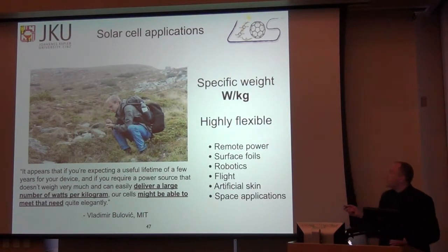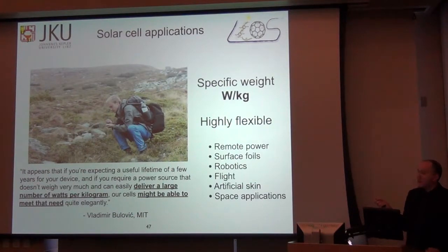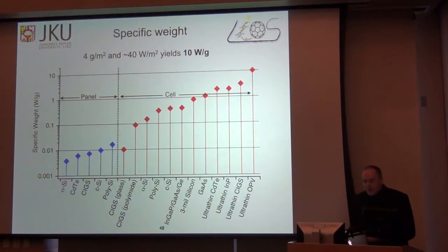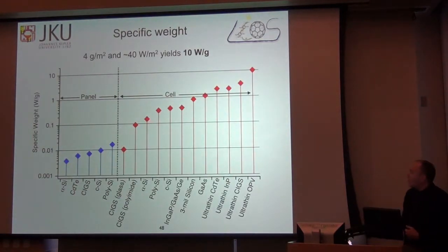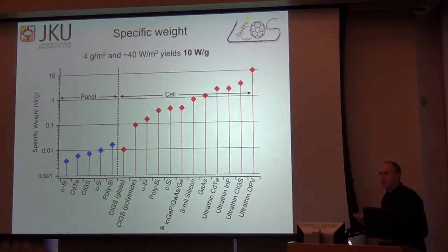So there's this alternative metric that's called specific weight, which instead of power conversion efficiency is the watts that you get out per kilogram. And if we compare, we have a 4% efficient solar cell, so we get roughly 40 watts per meter squared peak out of the device, but at 4 grams per meter squared, we wind up with 10 watts per gram, which is by far the highest power per weight from any photovoltaic technology ever, with a pretty rudimentary organic photovoltaic device.